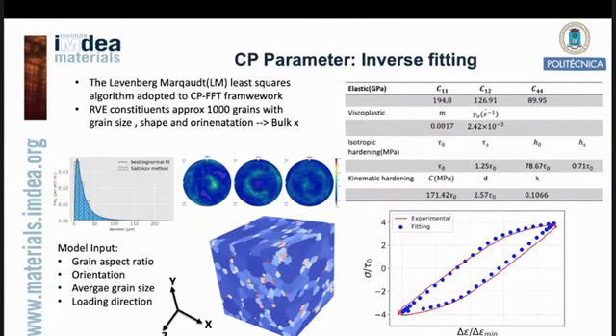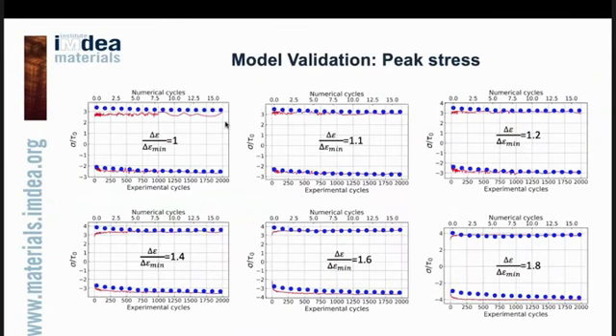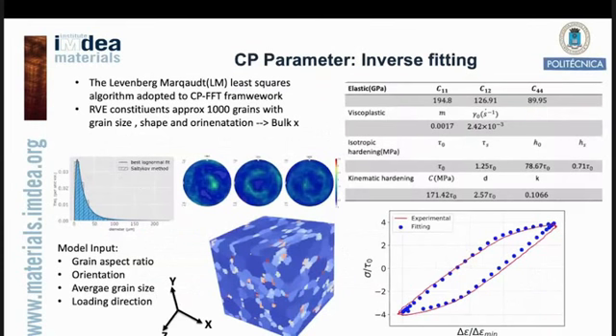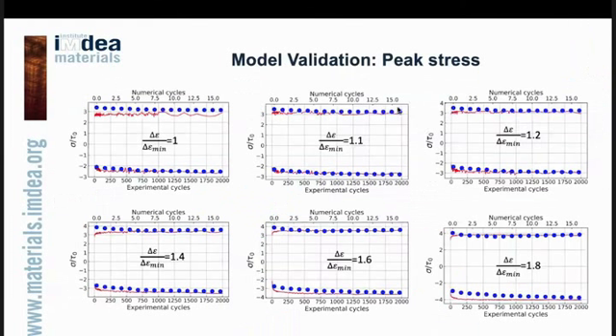Then we used different applied strains and checked the peak stress in each case. The red line is the experimental one, and the blue dots are the numerical ones. In each case, we are able to find the accurate peak stress, and at the same time the stable peak stress. So after the 15th cycle, the hysteresis loop has stabilized, and the FIPs in that stabilized loop have been used for fatigue life prediction. At the end of the 15th cycle, we have a quite stable response, and that has been used.